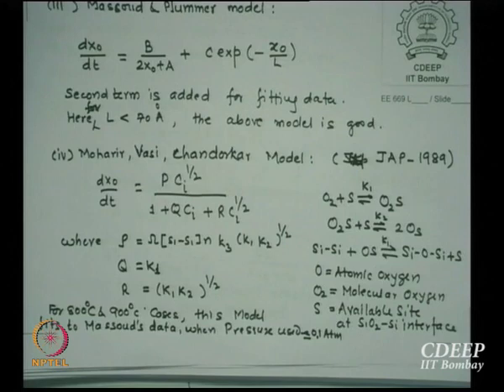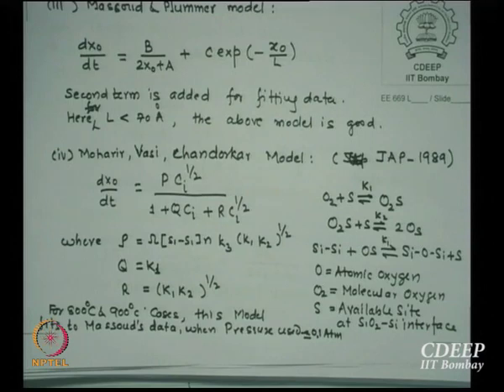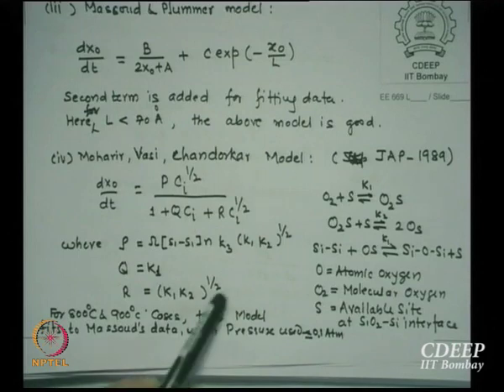We fitted this for 800 degree and 900 degree centigrade with the Masood experimental data, which he published for different pressures, but 0.1 atmosphere pressure is the best result they claimed. So we fitted our model to this, and by making proper choices of K1, K2 also, we derived what values we should have, and based on our analysis, we could get PQR values which fit thin oxide. So we could fit data up to 20 Angstroms of oxide thickness. Below 20, of course, our model also did not fit. For 20 to 40 or 60 Angstroms, our model fitted very well with the experimental data then known.